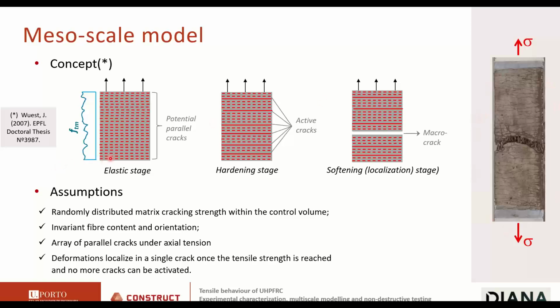And how does this work? We consider that the matrix cracking strength is randomly distributed along the specimen. Okay, so you have here a number of parallel potential cracks, some of which will be activated during the loading process.